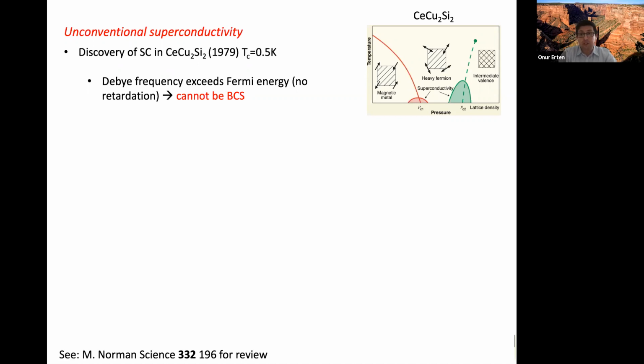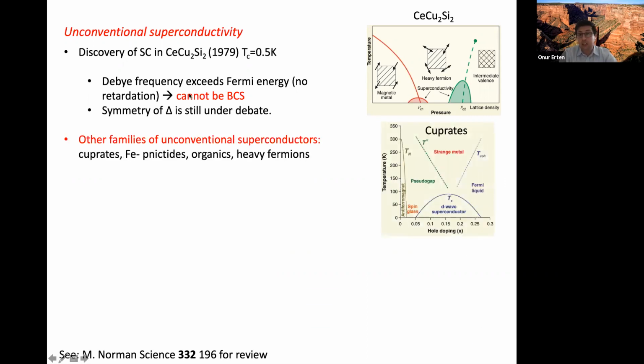By the way, the symmetry of the order parameter here is still under debate. It's quite surprising. People thought it was D-wave for over 30 years, but recently they realized that it's actually fully gapped, and it's not really clear what the symmetry of the order parameter is. It's for sure not an on-site S-wave superconductor, so what can give rise to fully gapped superconductivity in cerium copper 2 silicon 2 is still under debate. But what really kicked off the field of unconventional superconductivity is the cuprates.